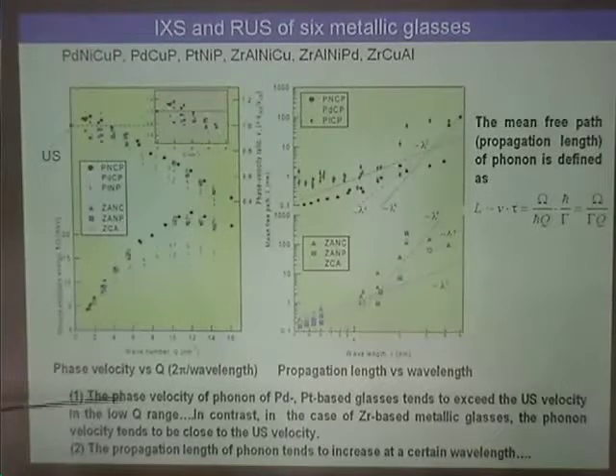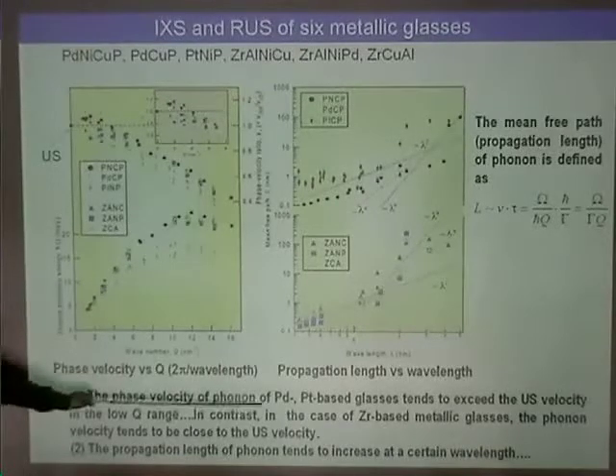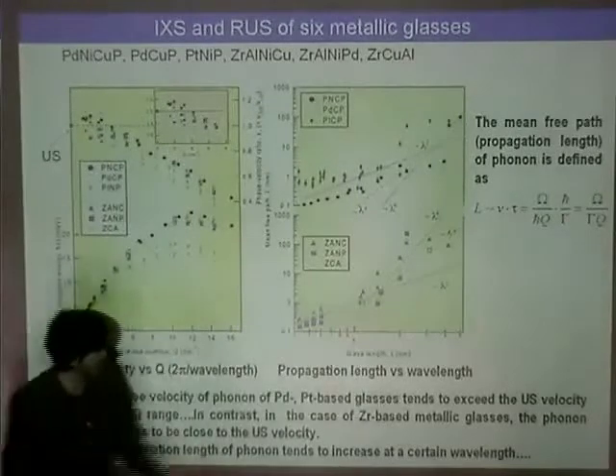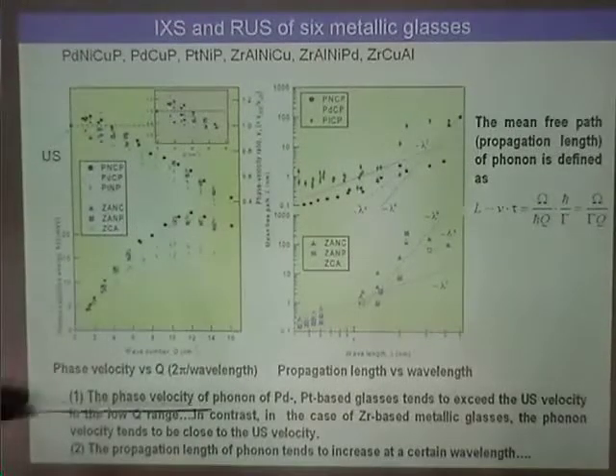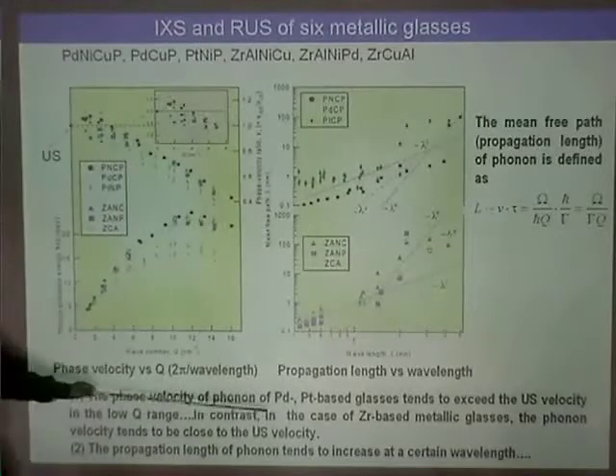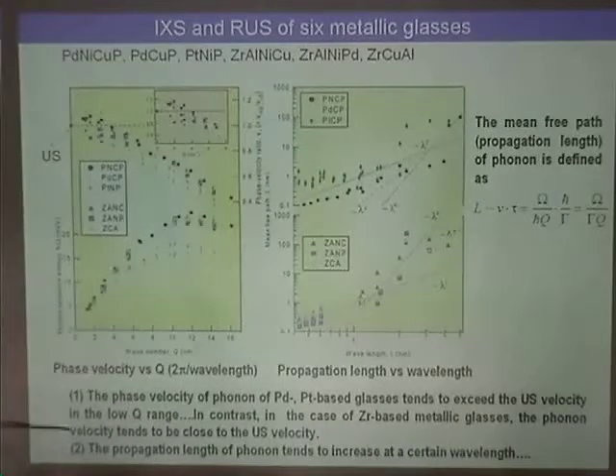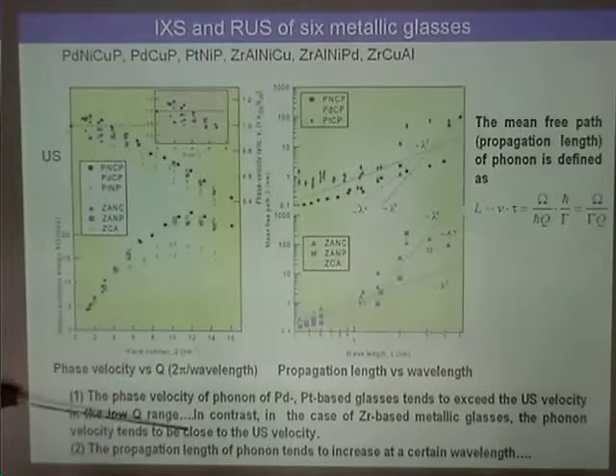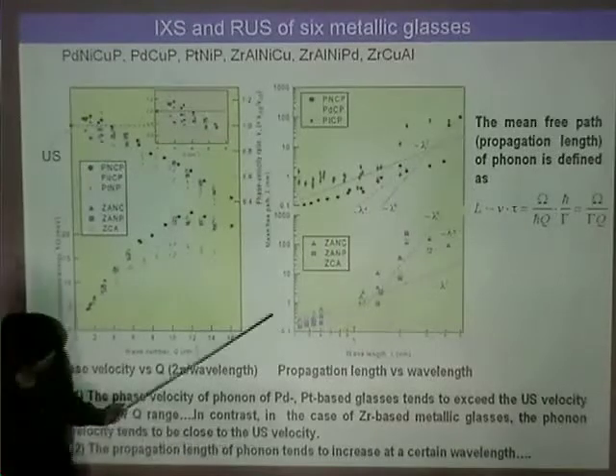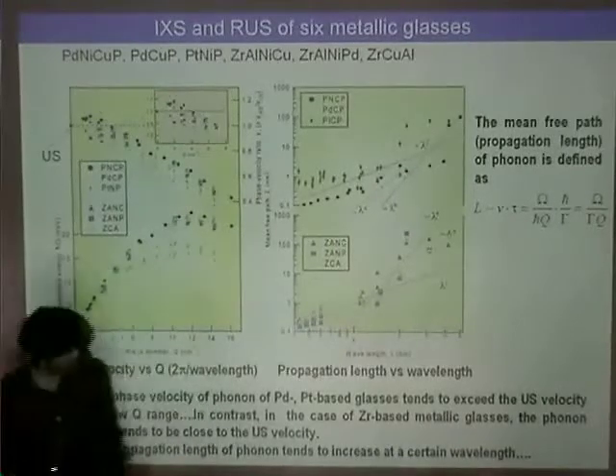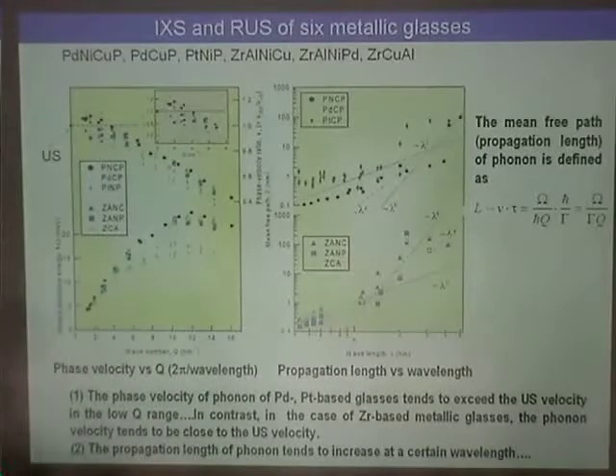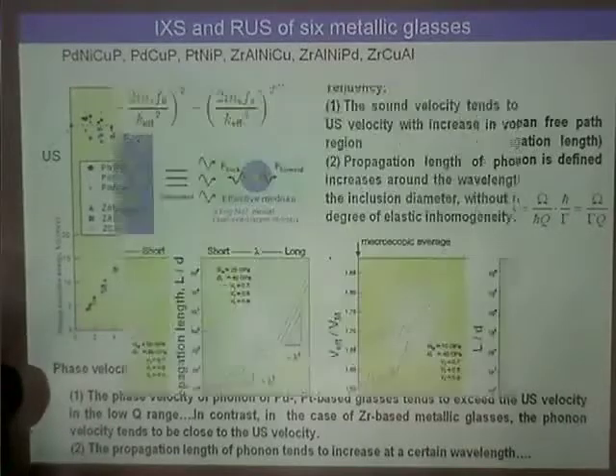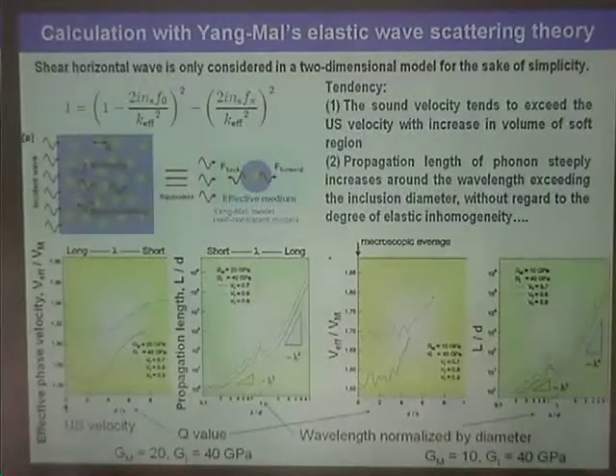The phase velocity of the phonon of palladium-platinum based glasses tends to exceed the ultrasonic velocity, but in the zirconium based metallic glasses, the phonon velocity tends to be close to the ultrasonic velocity, and the propagation length of phonon tends to increase at a certain wavelength. So we try to explain this phenomenon by using the continuum elastic scattering theory.